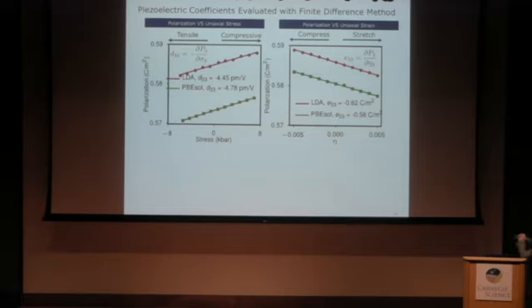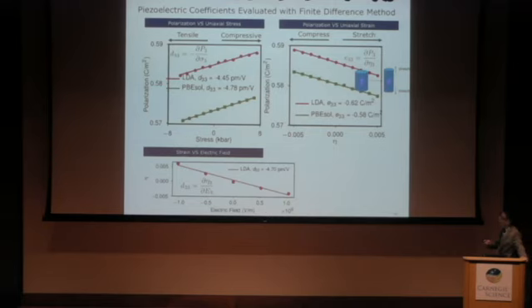So when we stretch the material, that is apply a positive uniaxial strain, the polarization becomes smaller. When we apply a compressive strain with negative strain values, the polarization becomes larger. So it is indeed consistent with the idea of a negative longitudinal piezoelectric response, as I showed earlier. We also look at the strain change in response to an external electric field with the finite field method. It's a little bit challenging to get it converged, but at the end we get this nice linear relationship between the strain and the external electric field. As you can see, when we apply a positive electric field along the polar axis, the strain becomes smaller. Again, consistent with the picture of negative piezoelectric response.